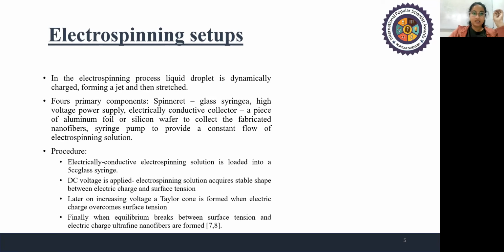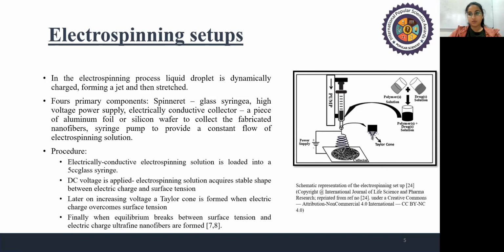So the procedure includes that the electrically conductive electrospinning solution is loaded into a 5 cc glass syringe. DC voltage is applied. The electrospinning solution acquires a stable shape between electric charge and surface tension. Later on, the increasing voltage forms a Taylor cone, when electric charge overcomes surface tension. Finally, the equilibrium breaks between surface tension and electric charge, and ultra-fine nanofibers are formed. So here we can see in the picture as well that there is a pump, a power supply, syringe, Taylor cone, and also the polymeric solution, which is forming ultra-fine nanofibers.